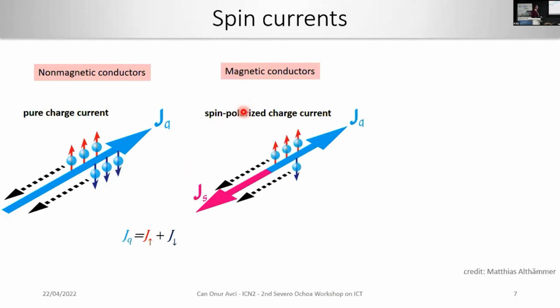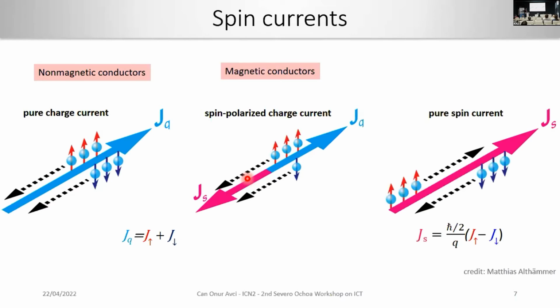However, if you do the same experiment in a magnetic conductor, due to the imbalance between the minority and majority states of the bands, you will have a net spin current that accompanies the charge current. So this is one easy way to generate a spin polarized charge current, or let's say a spin current, but that always comes with a charge current. But the ultimate goal here is to find mechanisms that could lead to a pure spin current without moving charges, which means you need to be able to move charges with oppositely polarized spin in different directions, so that you have a net spin current but no net charge current occurring. This lies at the heart of spintronic memory devices that I'm going to explain later on.